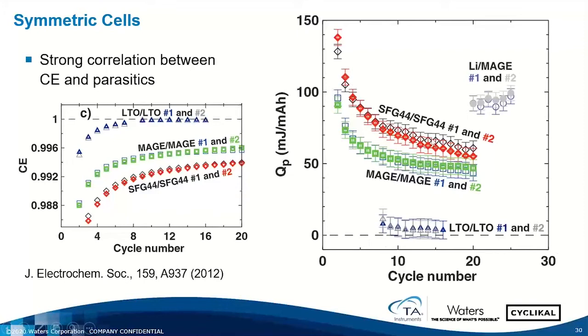You can see for the high surface area graphite, the thermal power, the thermal energy is considerably larger than the lower surface area. So this is a validation of what has been known, that high surface area materials generally are much more problematic in obtaining high cycle life relative to the low surface area materials, and this demonstrates that.